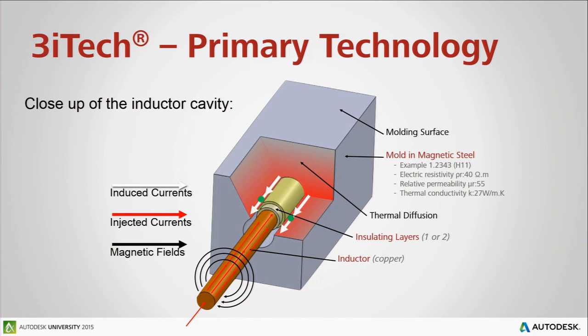If we take a closer look at what happens inside the mold, the idea again is to drive a magnetic field within the channel. When that magnetic field is very well driven and calculated, we know exactly what's going to happen: how fast we're going to heat the surface, how well we're going to heat it, and what it will take to cool it down. That is very important, and that is why we're spending time with Autodesk. Because if we can control this before making a mold, we have a very clear image of what happens in the tool before any serious investments.